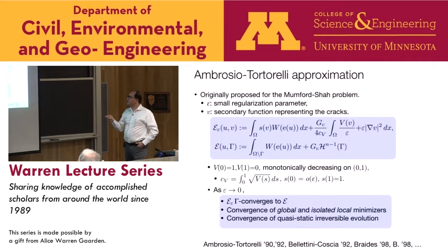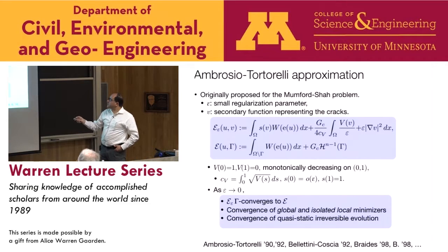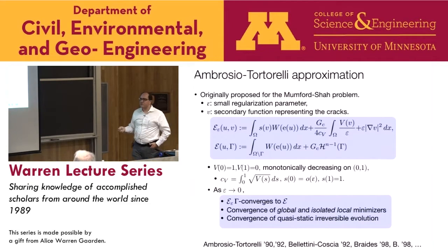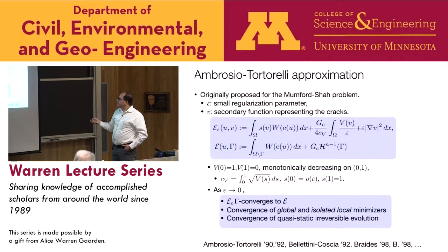And it turns out with the proper scaling, that is V squared over epsilon plus epsilon gradient of V squared, you can actually show rigorously that when you take this energy and you minimize it with respect to U and V, and then you send epsilon to 0, then the U that you get here converges to the U that you would get here. So the displacement in the phase field variable converges to the displacement in the variational fracture problem. But more interestingly, your V field converges in some sense. That is, the zones where V is not equal to 1 are going to concentrate around where gamma would be.